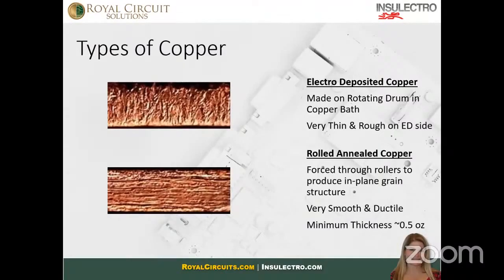Now, you can take advantage of these properties for different reasons. ED foils traditionally can be made thinner than RA foils, and if you know you have a bend-to-install type of flexible PCB and you're only bending this board once, you can get away with an ED foil and be just fine. Traditionally, rigid PCBs use ED foils extensively and only go to RA foils when they need the performance. But generally for flexible circuits, we want to give them the best possible chance to succeed. So the standard for flexible cores is going to be an RA foil. Those RA foils, like I mentioned, give us a lot of great benefits from a mechanical standpoint.